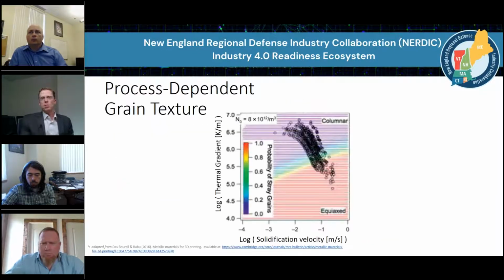A last consideration is that because of the large thermal gradients, you can end up with different types of grains within the metal, similar to what you would find in casting. Up here, on the vertical axis is the thermal gradient, or the log of the thermal gradient. A higher gradient goes up, a lower gradient is down on the vertical axis. On the horizontal axis is our solidification velocity. Very slow solidification happens on the left and very fast on the right.